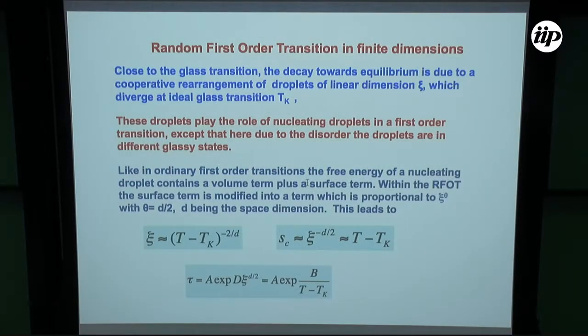These droplets play the role of nucleating droplets in a first-order transition, except that here, due to the disorder, the droplets are in different glassy states, as opposed to what happens in a normal, non-disordered first-order transition. That's why this is called random first-order transition. Like in an ordinary first-order transition, the free energy of a nucleating droplet contains, as you know, a volume term plus a surface term. Within the RFOT, the surface term is modified into a term which is proportional to xi to the theta, instead of being xi to the d minus 1, with theta equal to d over 2.